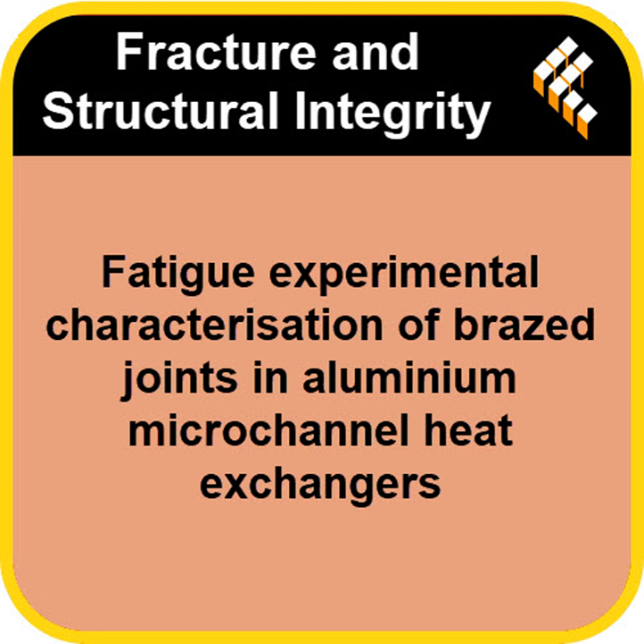Think about the rolled header material first. Okay. It starts out in what's called a cold worked state. That means the rolling process itself has strained and kind of disorganized the internal crystal structure, the grains. This actually makes it stronger initially. Right, work hardening. Exactly. But then when you hit that cold worked material with the high heat of the brazing cycle, around 600 degrees C for a few minutes, you trigger processes called recovery and recrystallization. So the heat basically lets the stressed grains relax and reform into maybe softer, less strained grains. It kind of undoes the hardening.